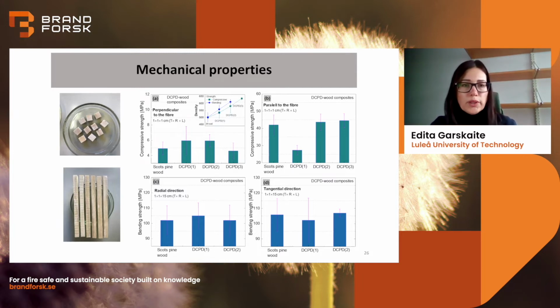That can probably be attributed also to the mineral. One reason we do not have such a big difference is that minerals are overall brittle, and their properties depend very much on particle sizes, on crystallinity, on composition. So to really say the main reason, we need to do a little bit more studies. On the other hand, wood by itself is an anisotropic material, and even within the same larger sample you can get slightly different properties. So the combination of these factors, achieving homogeneous saturation of the matrix and combining these probably a little bit conflicting properties of each material, gives a result.